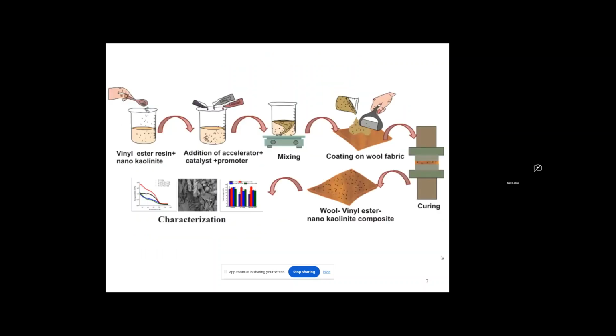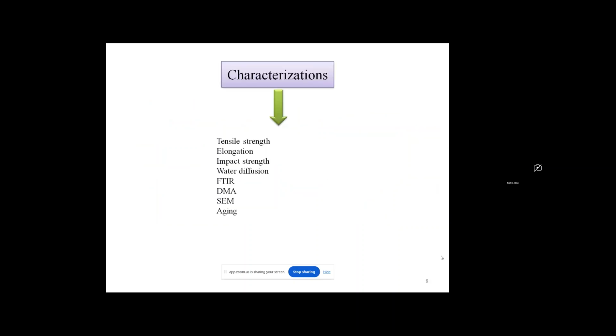So this is a schematic diagram of the process. Initially the vinyl ester resin and nano kaolinite were mixed. Afterwards we added accelerator and catalyst for curing. We mixed that, and coated the wool fabric with the resin along with the nano kaolinite. Then compression molding, and afterwards the composites were formed and further utilized for characterization. These are some of the characterizations: tensile strength, elongation, impact, water diffusion, FTIR, DMA, SEM, and aging.